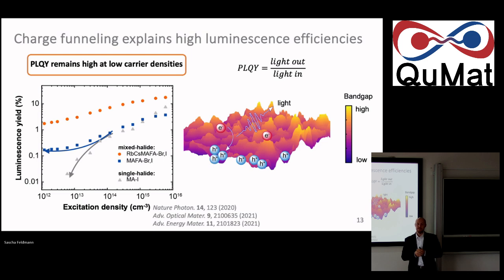From the modeling, can you tell which range of heterogeneity is actually useful? Because some of it might be detrimental, and you might want to make grains homogeneous with the microstructure. Yeah. So this for now just relates to the bandgap modulation from the halide mixing, right? So this is kind of separate even from grains and from the microstructure or any other distortions and so on. So here I take the grains not into account, because they don't seem to matter so much. These bigger features on the micron scale from the halide demixing seem to matter much more. That's quite nice.